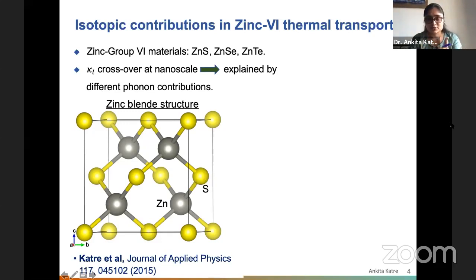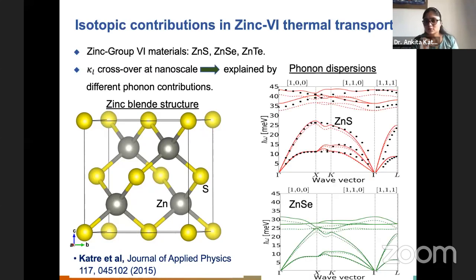So the first thing we said is that for the thermal transport we need the phonon dispersion. If you look at the phonon dispersion of these materials, I have pulled out zinc sulfide and zinc selenide here, and there's a reason for that. This graph shows the phonon frequencies as a function of wave vector, along a particular path of the Brillouin zone. The first thing we see is that there are no negative frequencies. That means the structure is stable. The dotted and the full lines are for different exchange correlation functionals used in this study. We needed to understand how LDA and PBE actually affect the thermal conductivity calculations. We have quantified this in our paper as well.